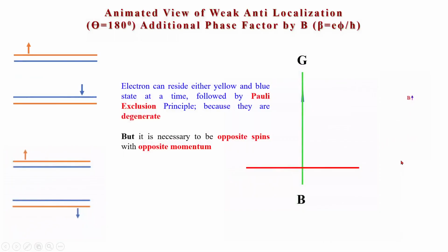Weak anti-localization signatures: with increasing magnetic field, the resistance increases, meaning the conductivity is suppressed, and it saturates after a certain value of the magnetic field. This occurs in topological materials in a very low domain of the magnetic field, typically observed in very ideal systems, approximately minus 0.5 to plus 0.5 Tesla. And this is the animation which has been shown here.